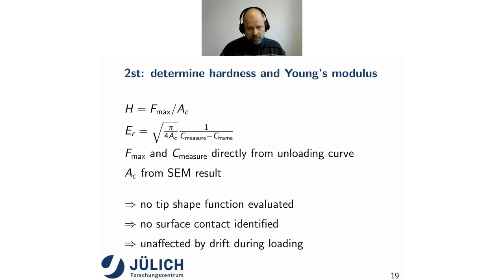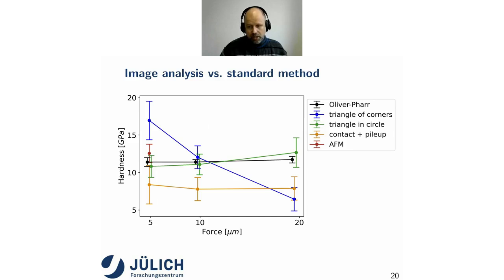And the important point here is that I did not have to know anything about the tip shape. Well, I knew that it's triangular, but nothing else. I did not have to identify the surface contact, and all the drift that accumulated during loading did not enter into my evaluation. So those points are rather good. But the real test is how does this method compare to the traditional way of using what is called the Oliver-Pharr method.